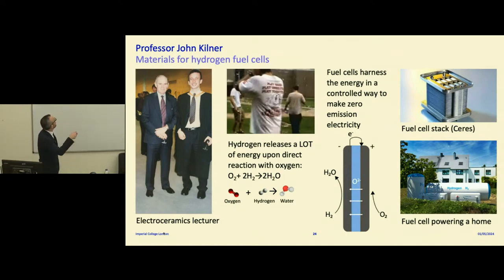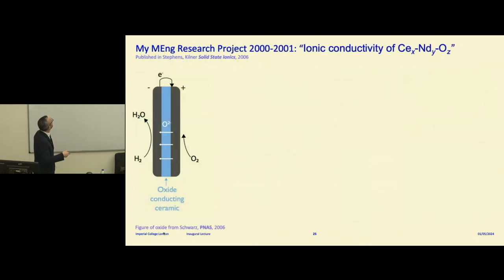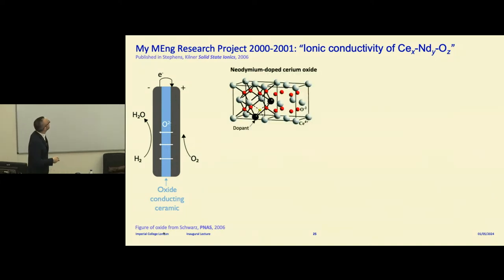So I was very excited when my favorite lecturer allowed me, well, I'm not sure if it was him, it was probably the master's project coordinator at the time, to do my master's project with him. We were looking at the materials you use for this membrane. We were looking at oxides, a mixture of metal and oxygen, that were doped, neodymium doped cerium oxides. Usually when you put in a dopant, you make a vacancy, like a hole in the structure. When you heat it up, the oxygen ions go through this. And this is really important in order to allow this fuel cell to work.